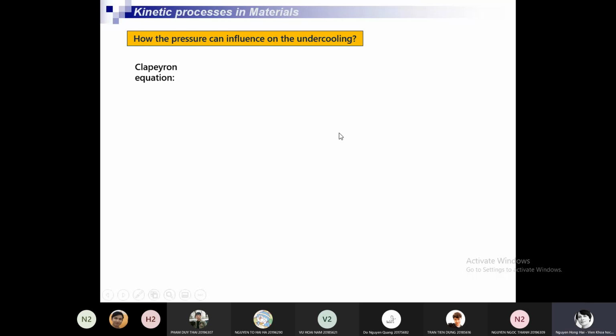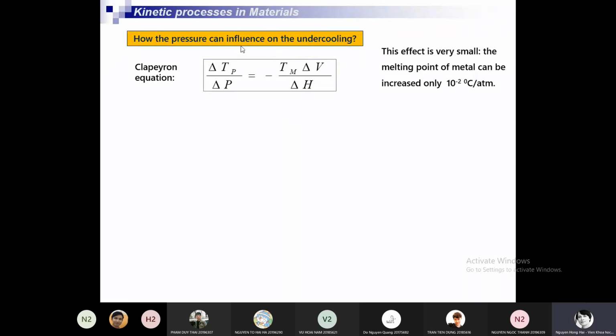So, the next question, how can the pressure influence the undercooling? Pressure. So we have the Clapeyron equation like this. Delta T, the increase in undercooling because of the pressure, over delta P is Tm, the equilibrium melting temperature, with the change in the volume and the change in the enthalpy. This equation shows that this effect is very small.